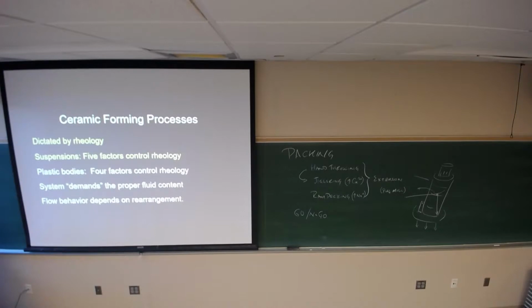on something. So, forming processes, we would argue, are dictated by rheology. There are 5 factors that control suspension rheology, which you already know. There are 4 that control rheology. That means that the system demands certain water content. We have the illusion of controlling the water content of plastic bodies. It is an illusion. You put more water in than it needs, it's sloppy. It doesn't work, right? Because it doesn't care whether you think it needs more water. It needs the right amount of water to work. You don't put enough water, then it's crumbly or doesn't form well or it tears, right? And it has to do with changing that rheological behavior.